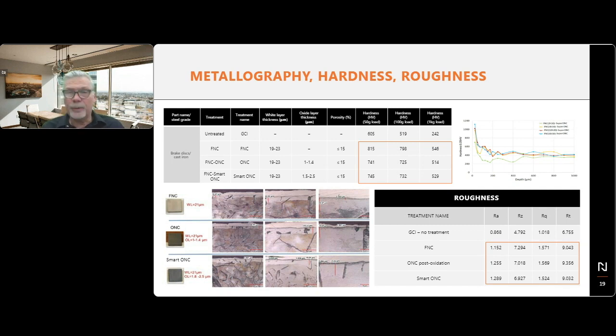As for roughness, roughness will always increase after nitrocarburizing. It does increase as well after nitriding, and the amount of roughness increase that you would expect varies on the original roughness. So basically the rougher the surface, the increase of roughness may be exponentially higher. If the roughness is relatively low, this roughness increase will be much lower. However, there is a threshold under which you could have almost mirror polished surfaces. Basically the growth of roughness will remain approximately the same, similar at least.